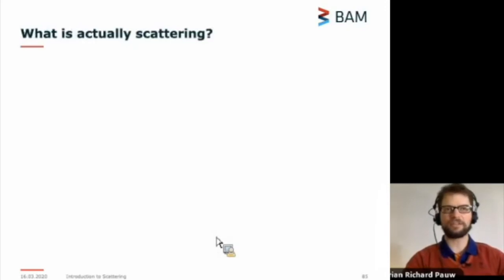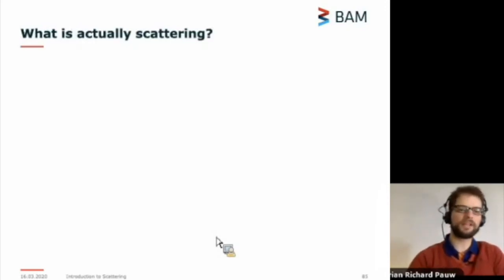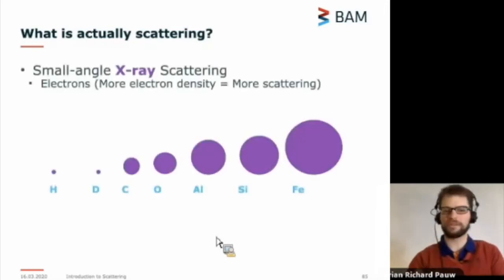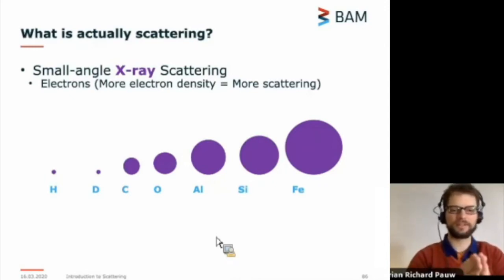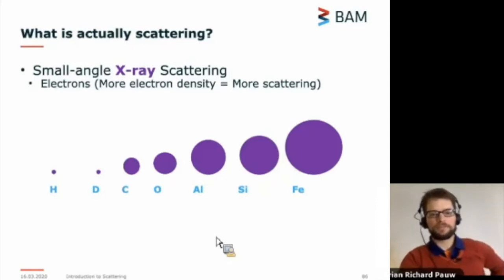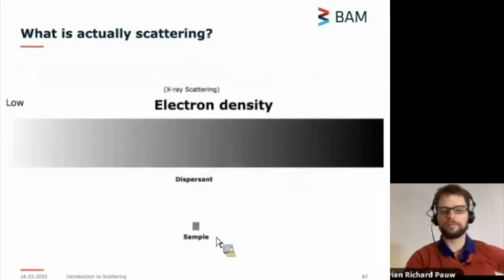But what is actually scattering here? Well, I mentioned that we are scattering from the electron cloud around atoms. And that means that if we have heavier atoms, then we get more scattering from there. It's not exactly true. We are actually scattering from the differences in electron density, the contrast. You can imagine what that looks like for a sample of a particular electron density in different media. If we have a large difference in contrast, then things are very easy for us to see. But if you have a sample which is very close in contrast to that of the surrounding medium, things get much harder.